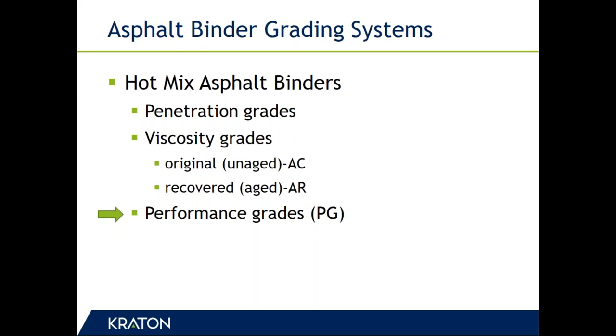In the late 1980s and early 1990s, the Strategic Highway Research Program, or SHRP, came along, and one of the technical research areas was asphalt. They spent about $50 million over 5 years to evaluate asphalt and developed a specification, which was referred to as a performance grade specification, or PG asphalt binder spec, which we have been using now for over 20 years in Texas.